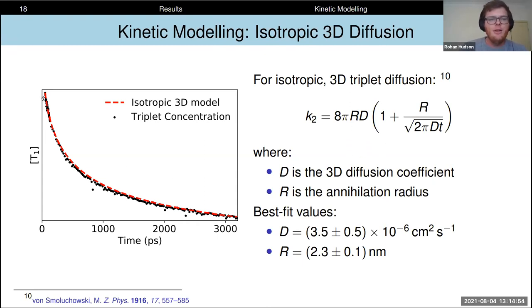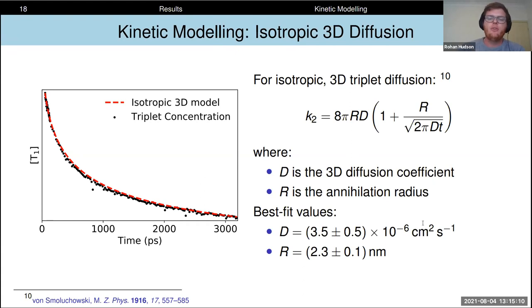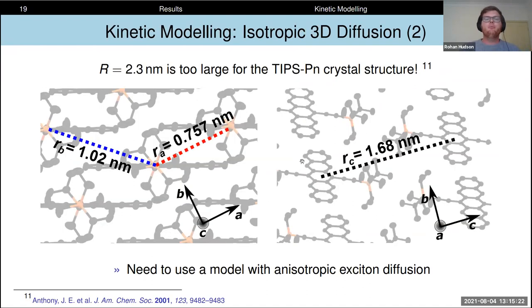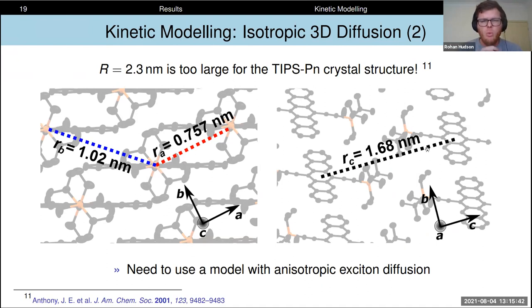Starting with the simple isotropic model, k₂ takes a mathematical form where D is the diffusion coefficient and r is the annihilation radius — the minimum intermolecular separation needed before two triplet excitons can interact and annihilate. If we try to fit this model to our data we do get quite a good fit, and our best-fit diffusion coefficient on the order of 10⁻⁶ cm² per second seems reasonable for triplet exciton diffusion in organic semiconductors. However, the best-fit annihilation radius seems too large at 2.3 nanometers — much larger than any intermolecular separation in crystalline TIPS pentacene — suggesting an issue with this kinetic model, most likely because it assumes isotropic diffusion in a highly anisotropic material.